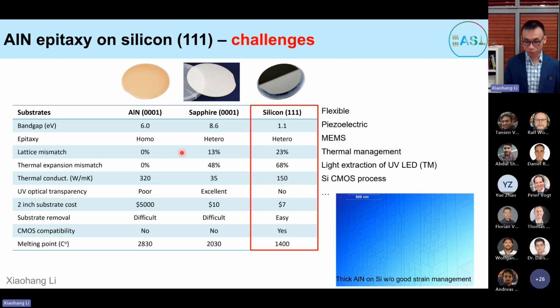A lot of the devices, including LEDs, the visible LEDs and UV LEDs, are made on sapphire substrate. Today it is very, very cheap. You can go to 12-inch, right? Although nobody is making LEDs on 12-inch, the 12-inch sapphire substrate is available. But it has other drawbacks. For example, it is thermally insulating, right? And it has a certain mismatch as well. And also, it's very hard to remove aluminum nitride from the sapphire, right?